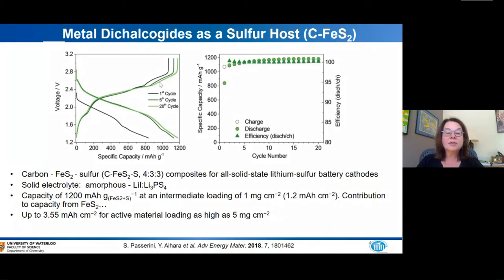Their data is shown here. This is the first cycle in black, and you can see there's quite a lot of irreversible capacity, so there's low coulombic efficiency, but then this mediates after about the fifth cycle. They achieve fairly stable capacity cycling over 20 cycles.